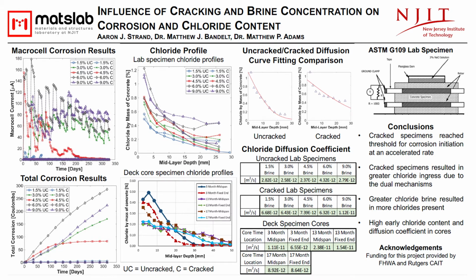Of the 3 specimens that had a macrocell current exceeding 10 microamps at the end of testing, the cracked 9% brine specimen had the highest average macrocell current with an average of 85 microamps during the wetting part of the cycle and 75 microamps during the drying part of the cycle. In the uncracked specimens, the 10 microamp threshold was not exceeded during the testing period.